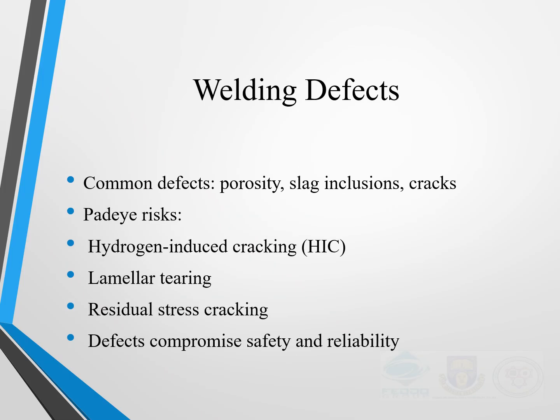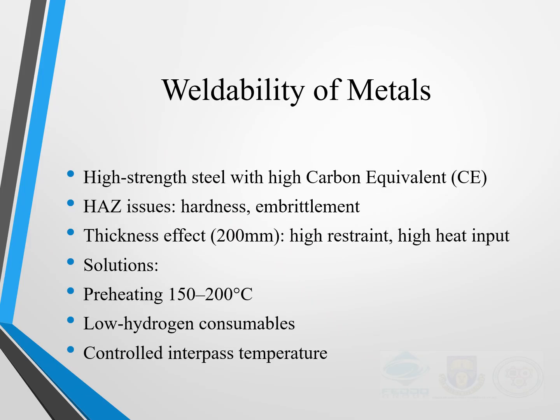Welding defects are major risks in such a thick and critical component. Common defects include porosity, cracks, and lack of fusion. For the pad eye, the biggest risks were hydrogen-induced cracking, lamellar tearing, and residual stress cracking due to the thickness and restraint. These defects are dangerous because they compromise safety and could lead to catastrophic failure in service.